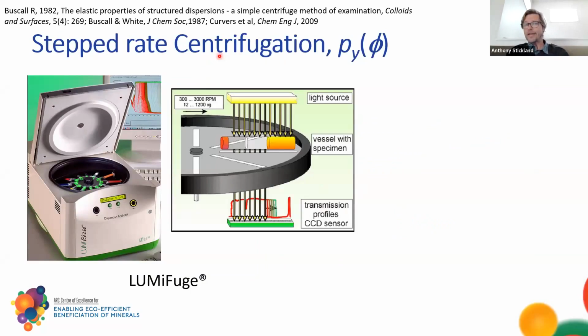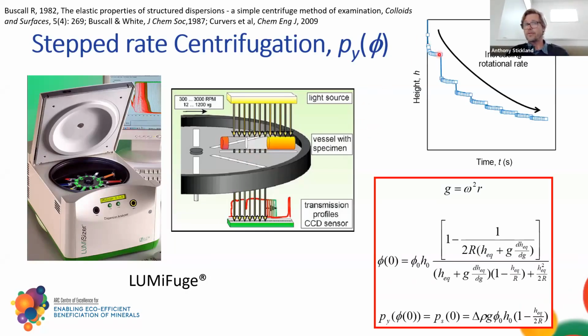We can also use centrifugation to look at the compressibility of a material. We put it into a tube. We've got this device in our lab called a lumifuge or a lumisizer. You put your suspension in a tube, it spins at high rates. There's a light source and a detector underneath, and so you can track the transmission through your sample, and you can track the height of the sediment as it's sedimenting. You can do that at a range of different rotational speeds, and from that equilibrium height at each rotational speed, you can back calculate the compressibility.